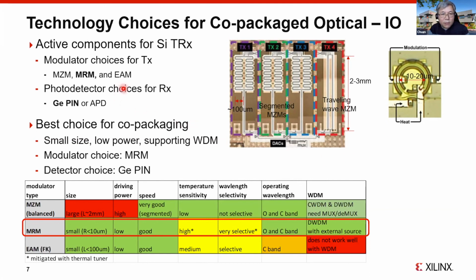The EA modulator is also compact and relatively small, usually less than 100 microns in length. But the issue there is that it only works for the C band, while for data centers, the O band is usually the preferred wavelength. It's also difficult to make an EAM work with WDM. Therefore, the best modulator choice for co-packaged optics is the micro-ring modulator.